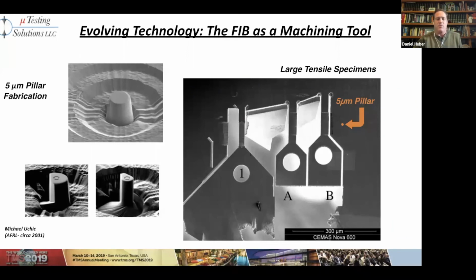And the process is that we would take a very small piece of material and mill all the edges away until we come up with a microcompression pillar, and then in testing they actually push down on the pillar and measure the mechanical properties. And then over here on the right hand side, Bob would continue to make some micro actuators for actually pulling and measuring the strain on very small specimens. So he's got marked over here a 5 micron microcompression pillar, which is a little circle, and then he's got these micro tensile specimens he's produced in 1A and B. So actually kind of like a little gripper they can pull a specimen.